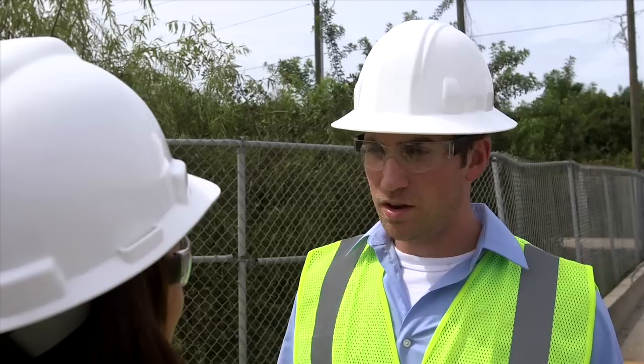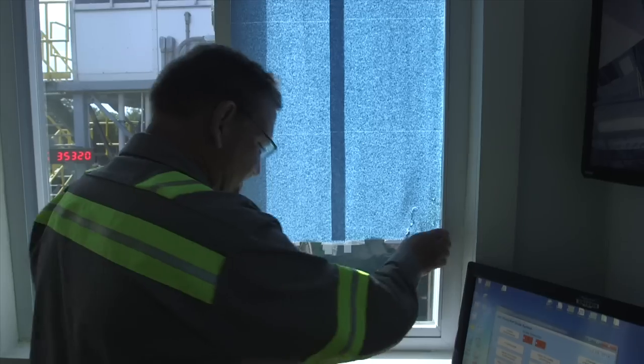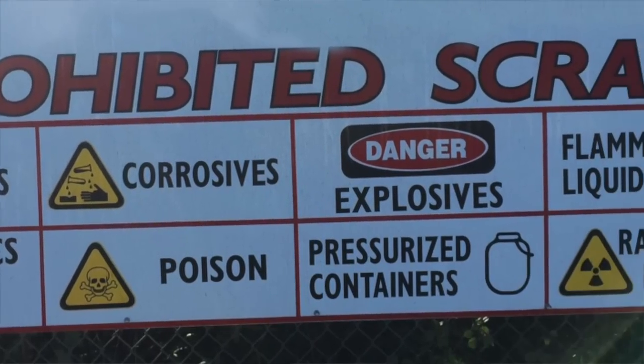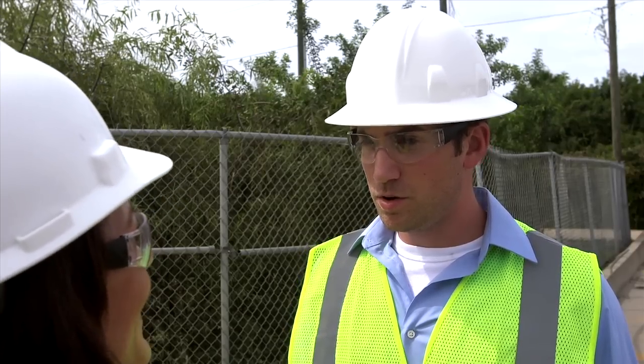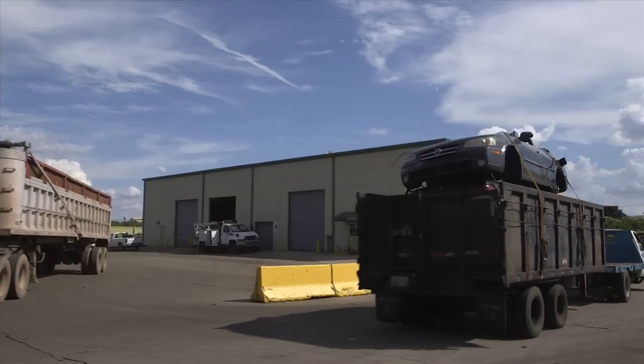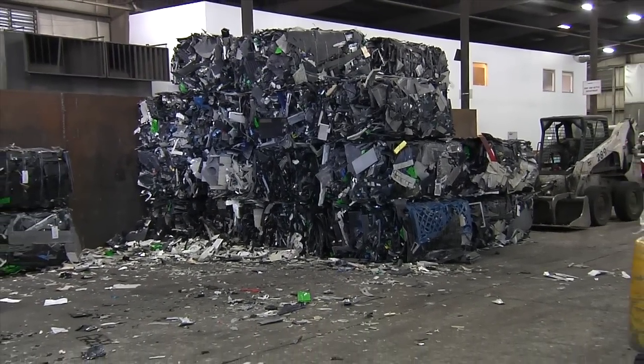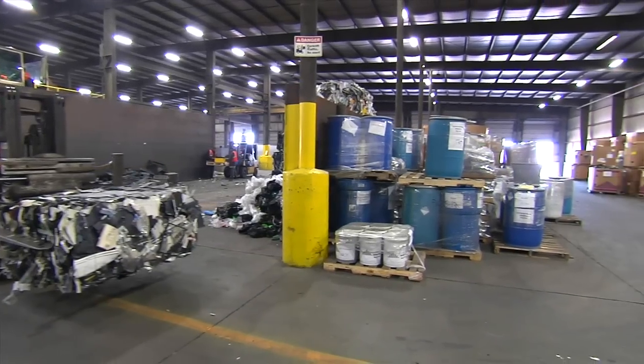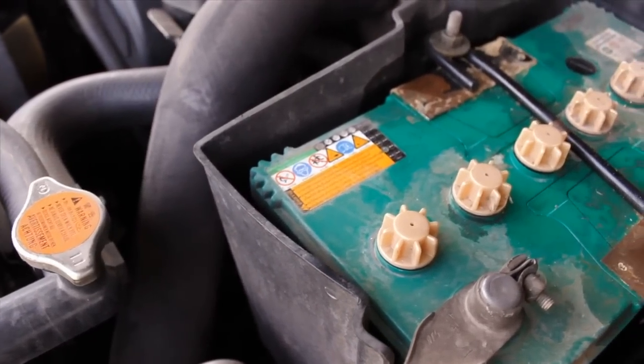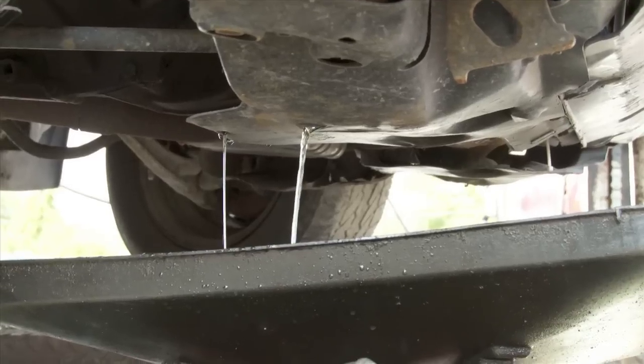Radioactive material could contaminate everything it comes in contact with, all the way to the steel mill. So the material acceptance policy is designed to keep the scrap yard safe and environmentally clean, and the product usable and consistent for the manufacturer. The recycler is processing these cast-off items to produce a feedstock for resale to a foundry or steel mill — the cleaner the scrap and the closer the specification, the more valuable it is on the market. Many of the products in use today contain substances of concern. These must be removed before entering the shredder to prevent release into the air, ground, and water — for example, refrigerants from air conditioners, lead from batteries, and mercury switches in automobiles and appliances. Material acceptance policies require suppliers to remove these components before they are accepted by the facility for shredding.